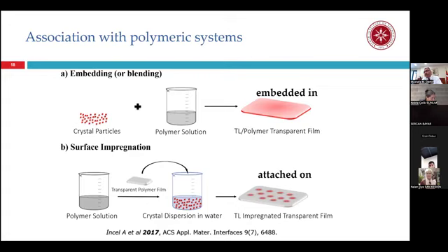So the question is, these crystals are known and synthesized. How can we associate them with polymers? One remedy could be as follows. You can dissolve crystal particles in a polymer solution, and you have a solution of polymers and pigment material. Then you cast it on a surface and obtain a film. This is called embedding or blending. The second could be surface impregnation. You have a film, and the film is immersed into a solution. Then the crystalline pigment particles adhere to the surface of the film.